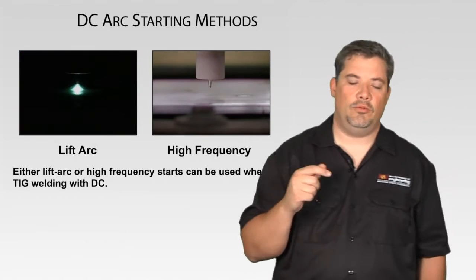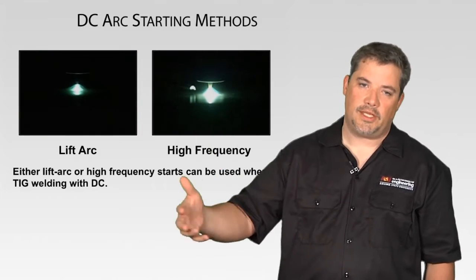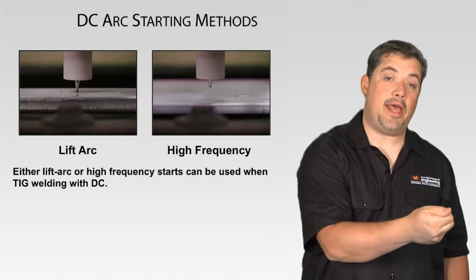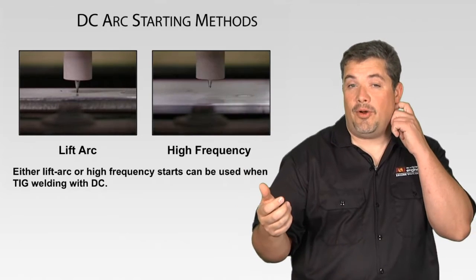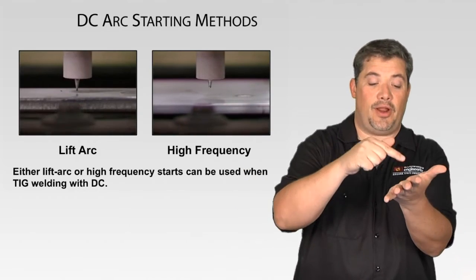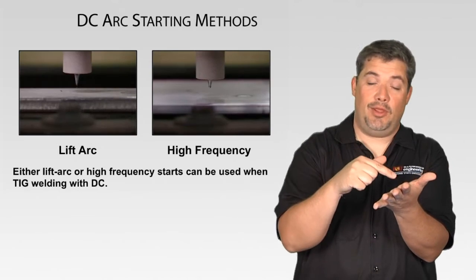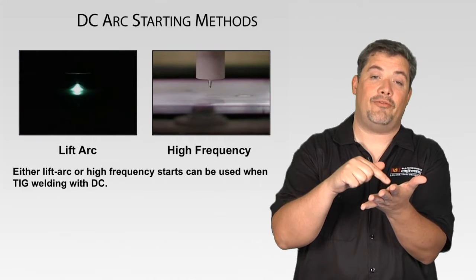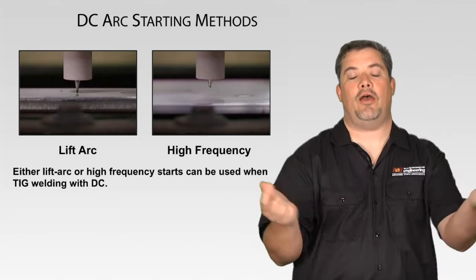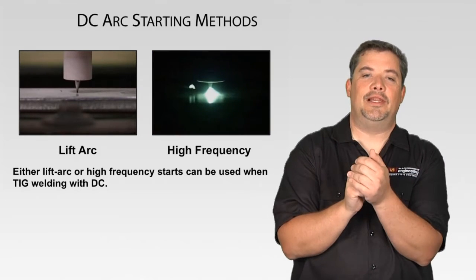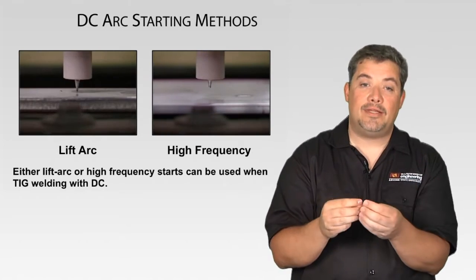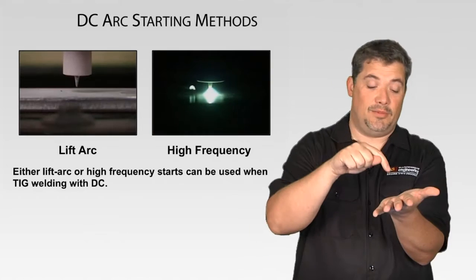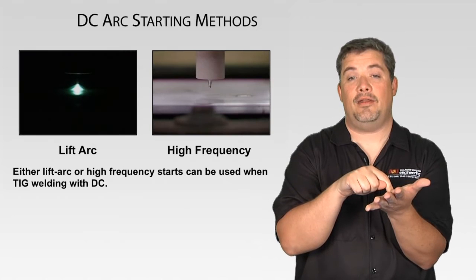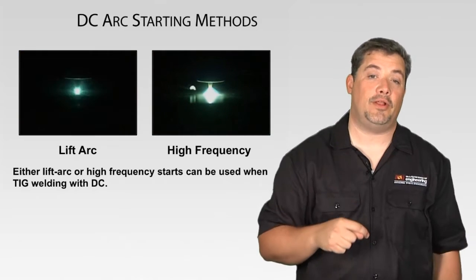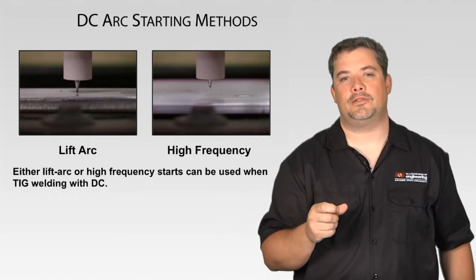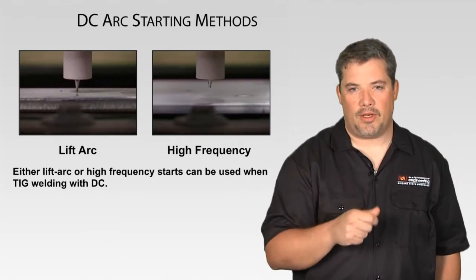Another reason for lift arc is the old school scratch start. When I took an old school stick welder and hooked a TIG torch to it with a gas hose, that old machine had about 80 open circuit volts. So I would do scratch start TIG like you did for stick welding, but you had to be extremely careful because you don't want that tungsten to break off or stick to the part, because then you have a tungsten inclusion and now a potentially rejectable weld. So they invented lift arc. What lift arc does is it takes it to about 8 open circuit volts with 0 amps, and the machine can sense, oh, you're dead shorted. I can turn on the amperage now, and it times it out perfectly so it's not sticky, and you can get a good arc start by touching the tungsten to the work without contaminating the part.